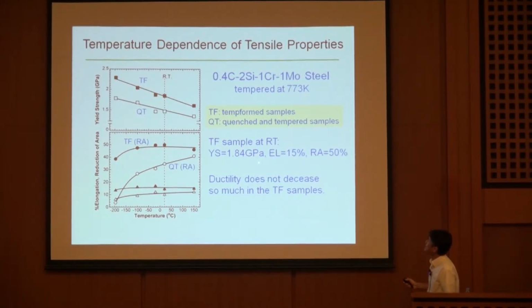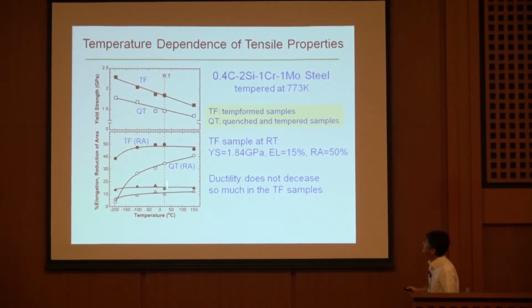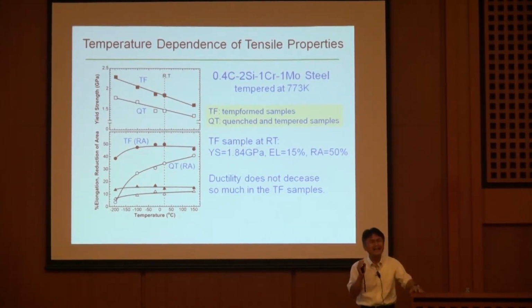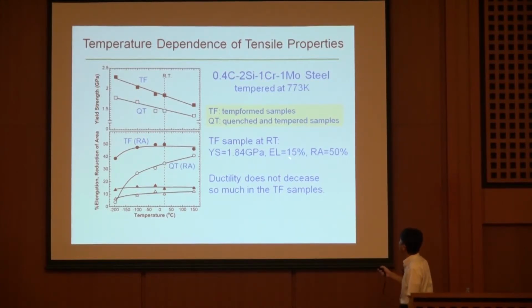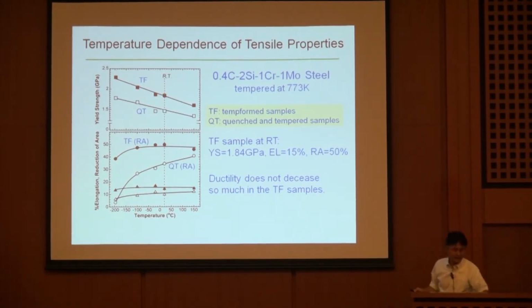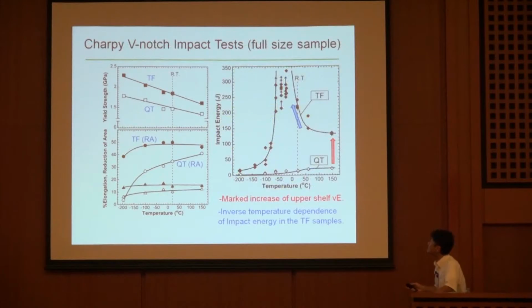Firstly, we have to check the yield strength. Yield strength here is 1.84 gigapascal, a little bit higher than the target of 1.8 gigapascal. And this is the elongation and the reduction in area. And how was the toughness? Here is the data: impact energy and the temperature. This is the conventional case, and this is the upper shelf energy portion.